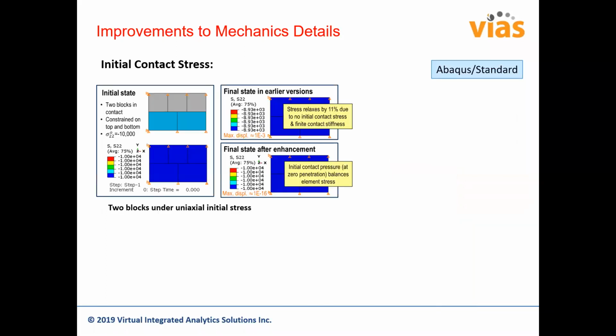This is the example where, in the initial state, you are basically confining the two bodies and you define some initial stress. That's showing you the stress at t equal to 0, initially. And once you see the final state, you see that previous releases used to give misleading results for the stress. There was a loss of 11% in them. But for the current release with the enhancement, you see the stresses are actually preserved properly because you have defined the initial contact stress between the two bodies correctly.